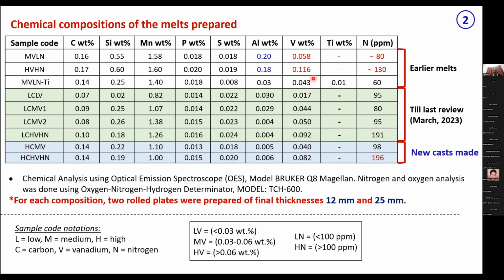We are varying vanadium almost over a wide range. So accordingly, naming the steel as L for low vanadium, M for medium vanadium, say 0.04 is our medium level, and another is high, H vanadium, that is 0.08 to 0.09. Similarly, we have varied nitrogen level. These steels are having quite high nitrogen. You see 196 ppm, 191 ppm, and we are using the nitrovan that Vanitec has provided to the R&D center of SAIL. So we are rolling them into two thickness plates, 12 mm and 25 mm, and studying the properties.